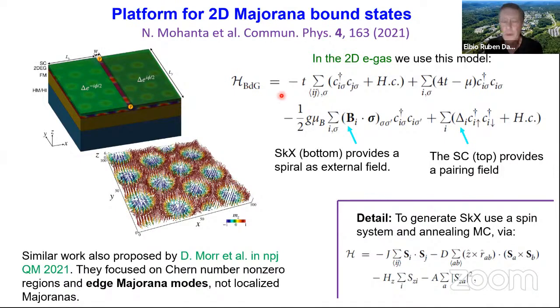So essentially we have a model for the 2D electron gas. You know, the theorists will immediately recognize the notation. This is a tight-binding term, canonical electrons moving. Then you have a chemical potential. The coupling with the exotic spin background because of the lower layer, and the coupling with a pairing field because of the top layer, right? So it's an electron gas that has a complicated spiral-like arrangement and has superconductivity from bottom and top. So the fact is that this geometry, remarkably, creates the Majoranas.